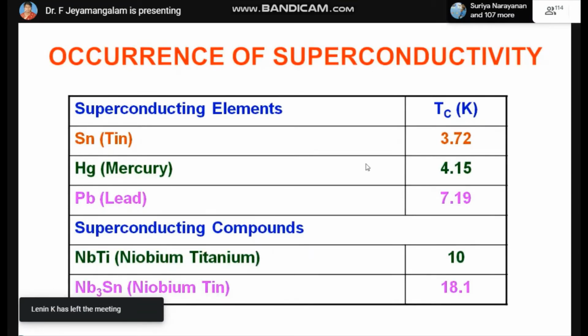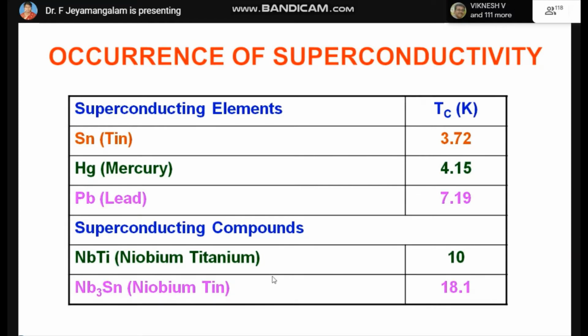Okay. So, I have shown you some pure elements which can become a superconductor at the critical temperature, that is tin, mercury and lead. There are some superconducting compounds, that is niobium titanium with 10 Kelvin, niobium tin with 18.1 Kelvin. Obtaining low temperatures like 4 Kelvin, 7 Kelvin is very, very expensive and very hard. So scientists were experimenting on other combinations of metals so that the critical temperature could increase. They were successful by making niobium titanium, which is an alloy, a superconductor at a sufficiently higher temperature, that is 10 Kelvin. So this is how superconductivity was finding its existence.